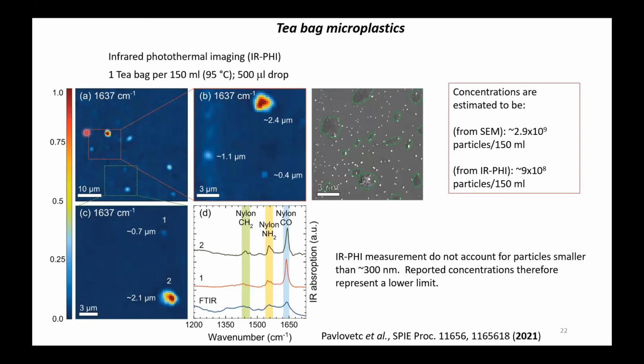We see a lot of particles present, of different sizes, from several hundred nanometers to a couple of microns. We can further take single particle infrared spectra to confirm that this is indeed all nylon, all released from the tea bag.